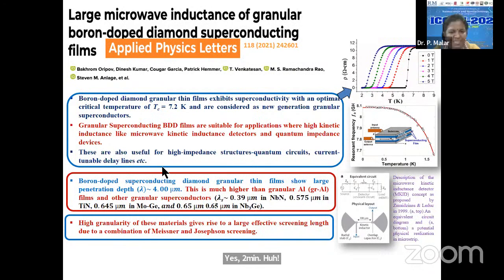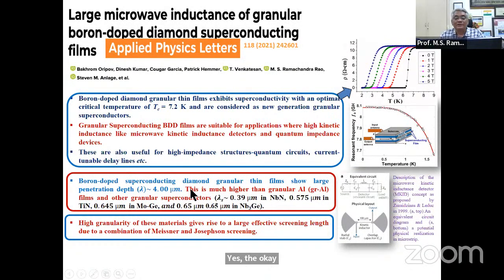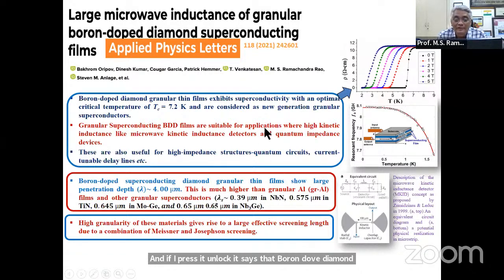So what they found was the penetration depth was almost 4 microns, which means this boron doped diamond also has very high microwave inductance. In fact, Professor Anlage says that boron doped diamond could potentially replace all the existing conventional granular superconductors, and it can be called a new granular superconducting material that can be used as a perfect connector possessing high kinetic inductance between 2 qubits in quantum circuits.